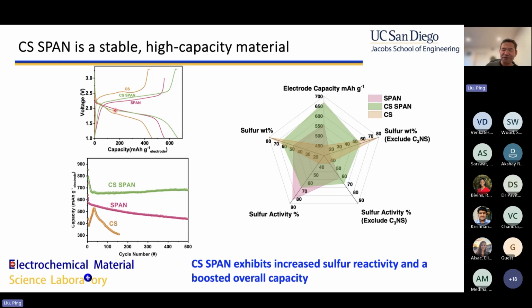Turns out that if we shuffle a lot of sulfur into the material, there's no magical pill. The material starts to behave like a mixture with the elemental sulfur, which will reintroduce a lot of the degradation mechanisms suffered by elemental sulfur. So what do we do?